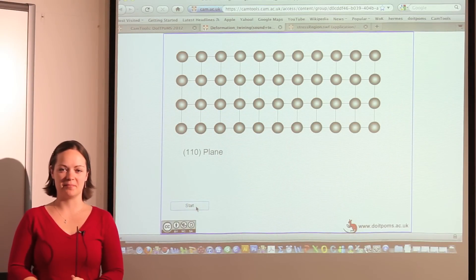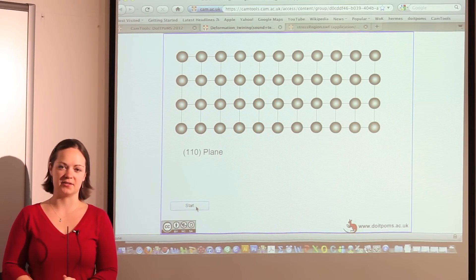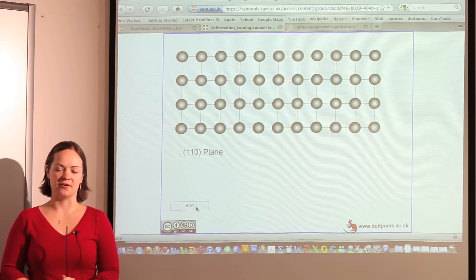We'll consider the room temperature case first. When I bent the bar, deformation twinning took place and we heard a characteristic crackling noise known as tin cry.